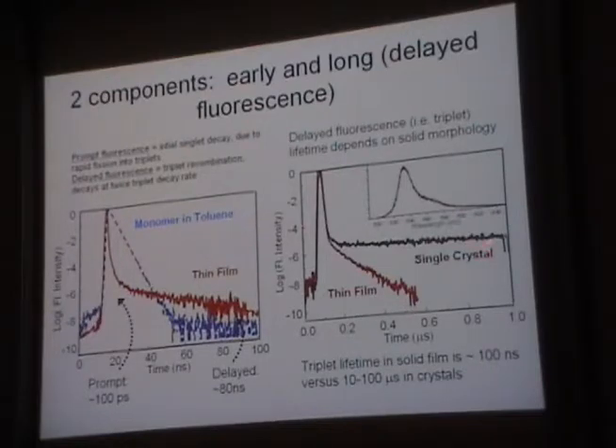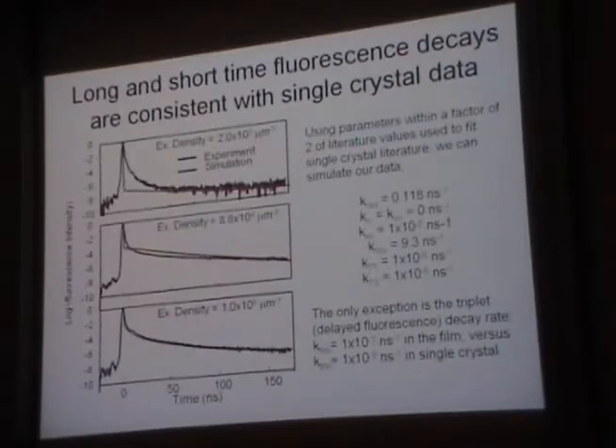One thing we did notice is if you do a single crystal and compare it to the thin film, the delayed fluorescence lifetime is much shorter in the thin film. It's not 100 microseconds, it's about 100 nanoseconds. So morphology does affect the triplet lifetime strongly. That's easy to understand, right? The triplets live a long time, they diffuse around, and if you made a crappy film, they're going to find all the crappy parts and deactivate there. But that takes hundreds of nanoseconds, or at least 100 nanoseconds, even in really poor films that my group makes. So single crystals again, 50 microseconds is no problem.